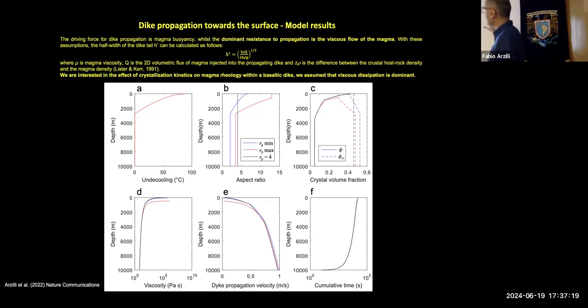So we put all this information into a dike propagation model. What we wanted to simulate was the propagation of a basaltic dike within the crust with 3 scenarios. The aspect ratio constant at 4, so despite undercooling increasing, kinetics will not change, so we have a constant aspect ratio during ascent. Then we consider the aspect ratio maximum, considering our experiments and other experiments performed on basalt, and therefore considering the approach to equilibrium really fast, we reach the maximum aspect ratio possible in the shortest time. And the aspect ratio minimum, that means that the disequilibrium takes longer, and so our basalt is not able to reach equilibrium quickly.